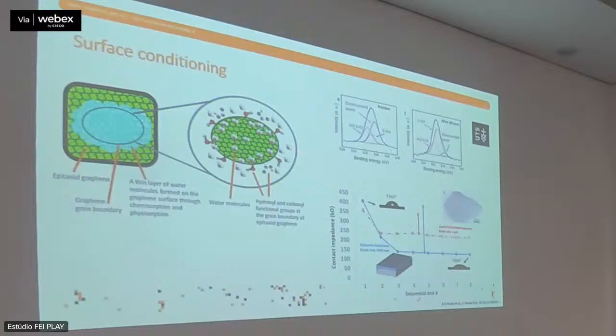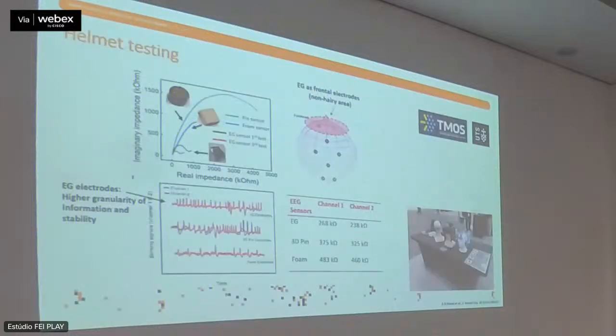Basically, our model is that we are functionalizing the edges and related grain boundaries of our grains. And little by little, we start to attract a thin boundary layer of water, making it better. That's what we see here. We have gone from a 70 degree contact angle down to 30 or less. And if you use a large grain size graphene, you couldn't do that much. By the way, this corresponds to a really important drop in contact impedance, which is what we're after. And after that, it remains really stable, which is of great help for what we're trying to do.